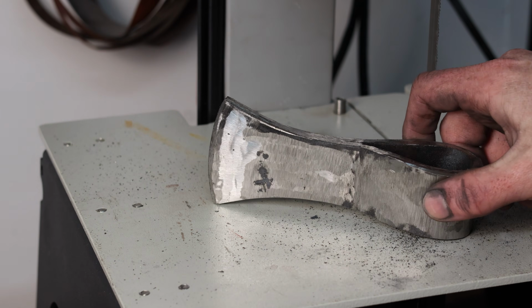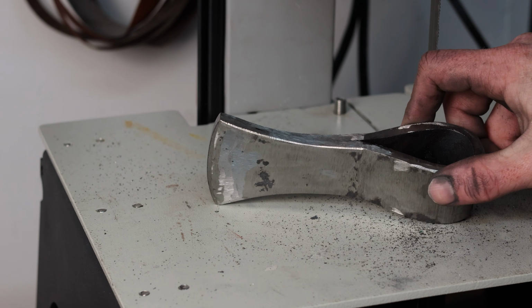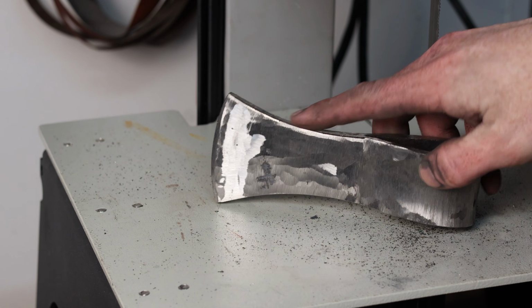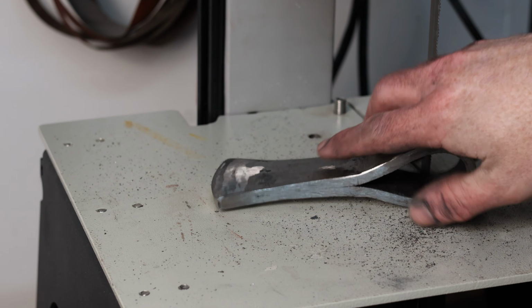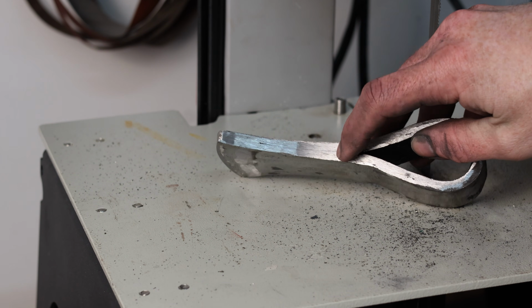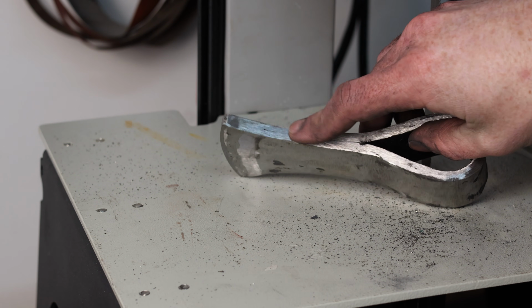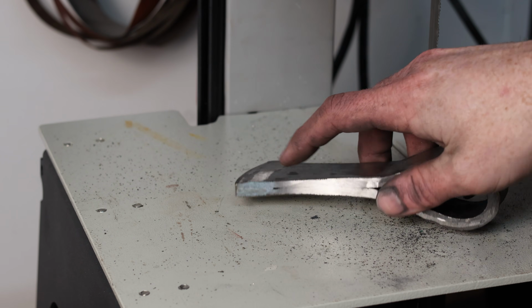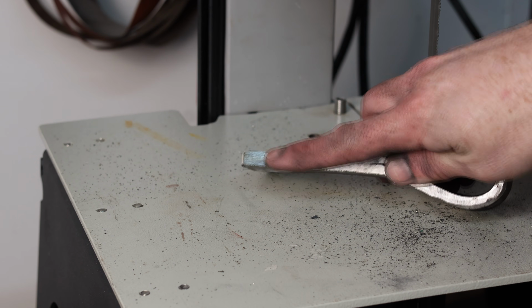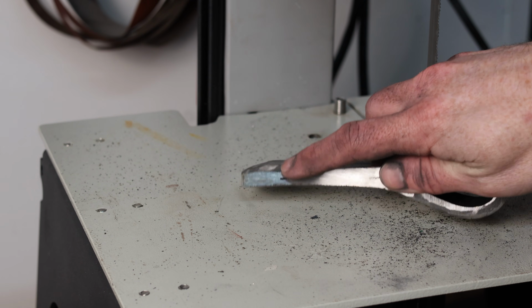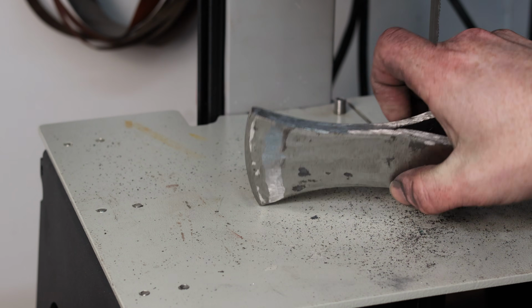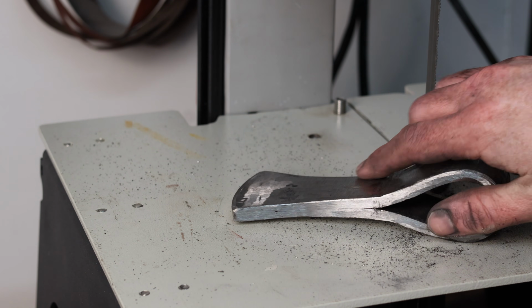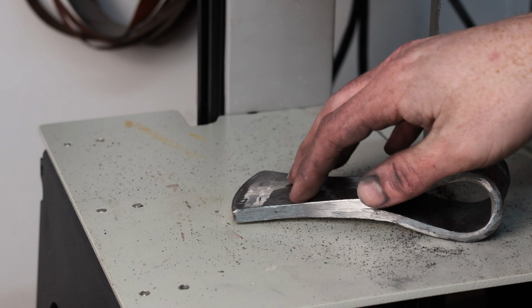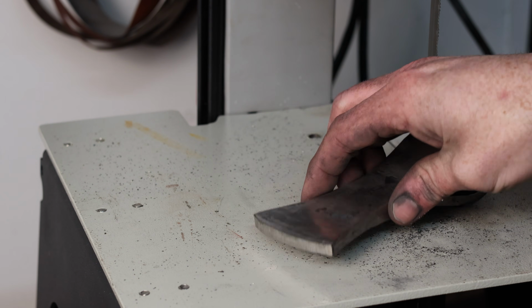All right, so this is very roughly ground down now, and I've been looking at the seams, and I've done quite a bit of grinding on these edges where those seams are, and I've got it down to where it's definitely disappeared in spots, but there's obviously one or two spots like here where the end of the bit must have been a little too thick to result in a good weld in that area. Got a little better on the other side. However, it wasn't a perfect weld. I think the bit itself got a pretty decent weld.